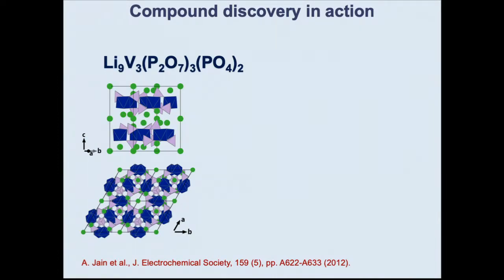So I want to show you just very quickly a few examples of that in action because now you can just let the computer play. The computer can take known compounds, apply these substitution rules on them, do calculations on them to see if they're actually stable, and then calculate their properties. And you can just let the computer run. So we discovered this battery compound because we wanted a vanadium redox couple. This looks like some totally weird chemistry, right? And that came from an iron-containing equivalent. And the computer just realizes it can often substitute iron for vanadium. And then when it calculates, it found that it's actually a ground state. So this compound was not at all known. But the computer basically found it just by using substitution rules.